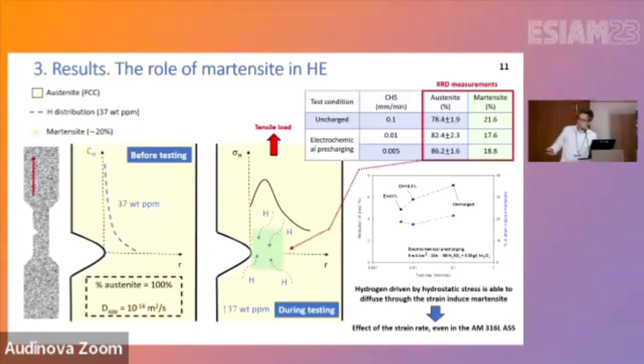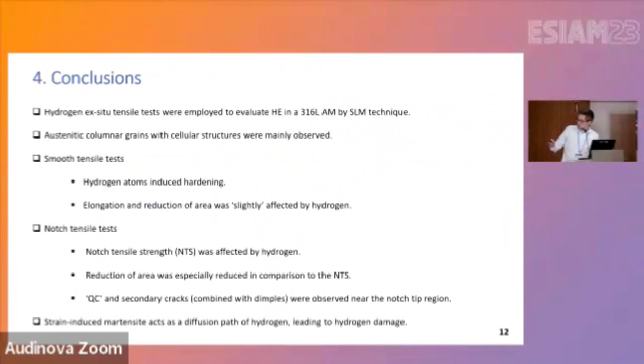And by means of this, accordingly, we can explain the effect of the strain rate, which contributes to justify the loss of ductility, especially in terms of the reduction of area. Because now, during the tensile test, hydrogen is able to diffuse by means of the strain-induced martensite, which is prone to hydrogen embrittlement.